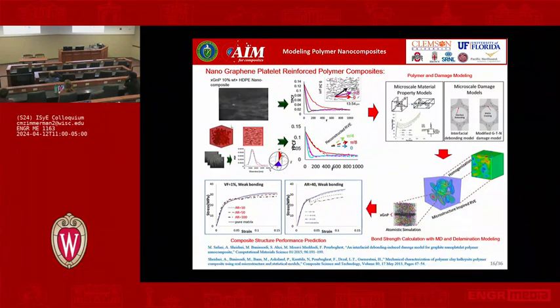Now I can do all sorts of tests on it, not just tensile tests. I can shear it, I can squeeze it, I can do whatever to it. One thing we have found out is, we can do sensitivity analysis, and what we found out is that depending upon the aspect ratio of the size of the platelets and its thickness, if you go beyond a certain aspect ratio, your property will be even less than the actual pure matrix. So you have actually defeated the purpose for that.